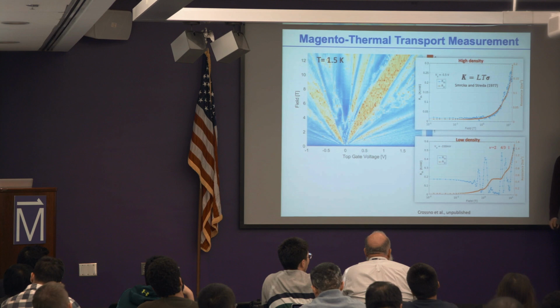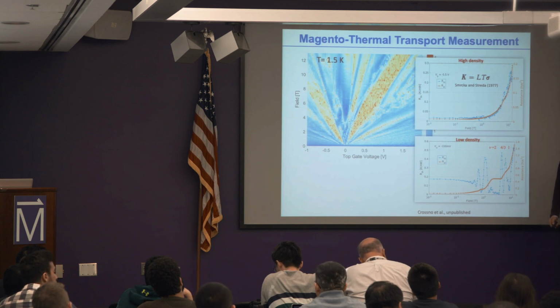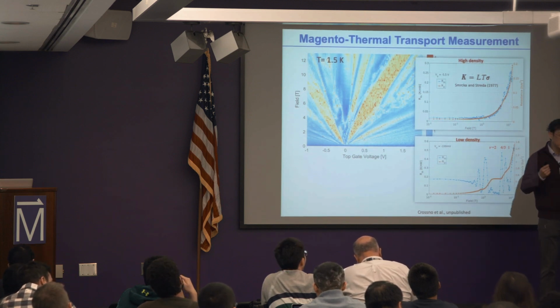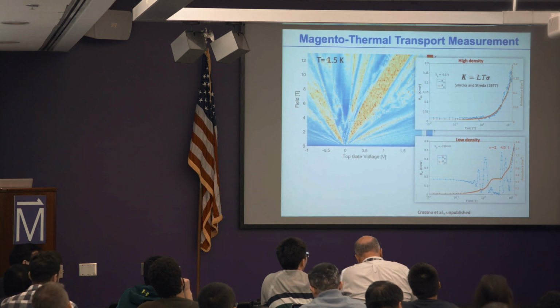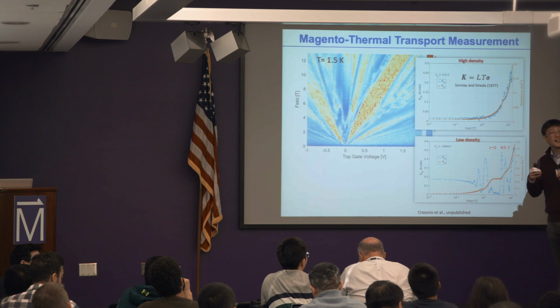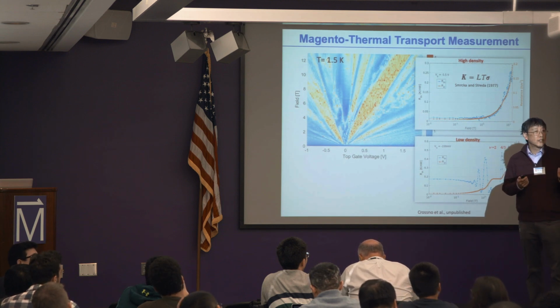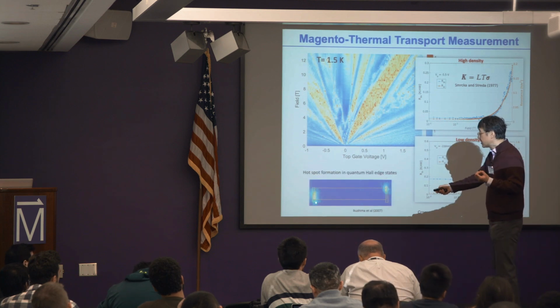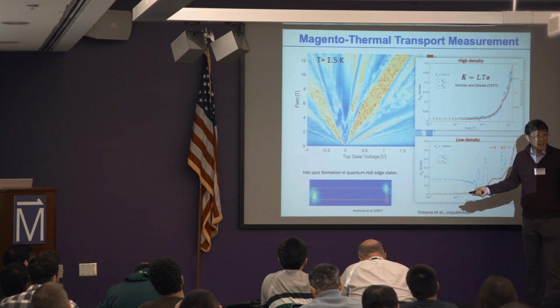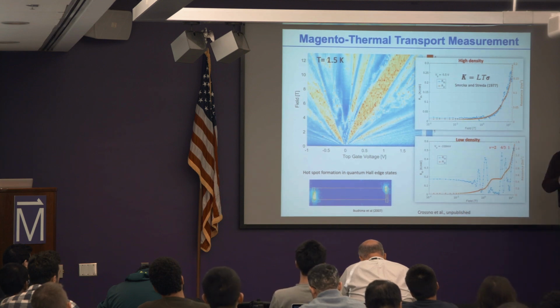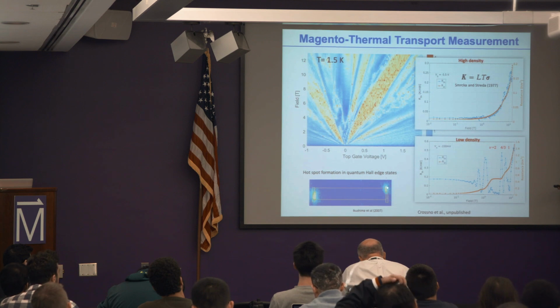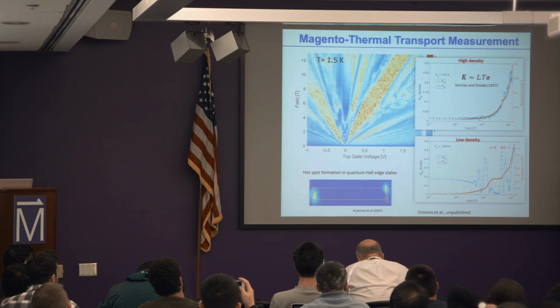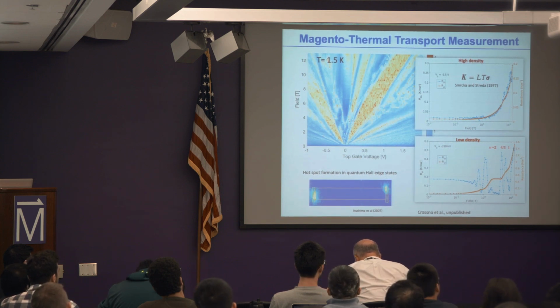It turns out this violation is not really intrinsic in some sense. With a little bit of detailed study, the way that we measure the thermal conductance is just through noise measurement. And this noise measurement, in Johnson noise measurement, is extremely sensitive to where the power dissipation is really happening. Of course, in quantum regimes, all this power is dumped at the contact because everything else is ballistic conductance. So it is expected that once you get into quantum regimes, most of the dissipation is happening at the contact near the hot spots, so not necessarily picking up some of the intrinsic things. But nevertheless, this is a good sense that we can see where the quantum effect sets in in this type of system.